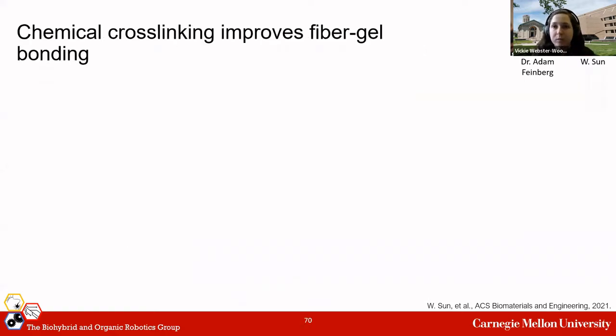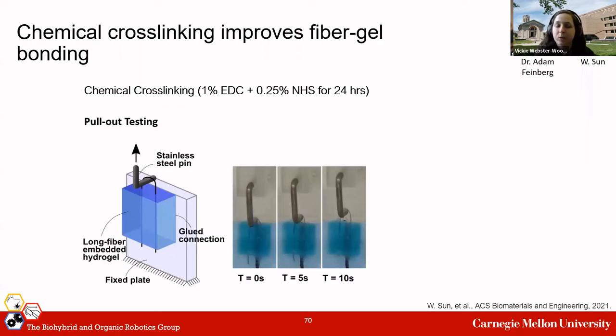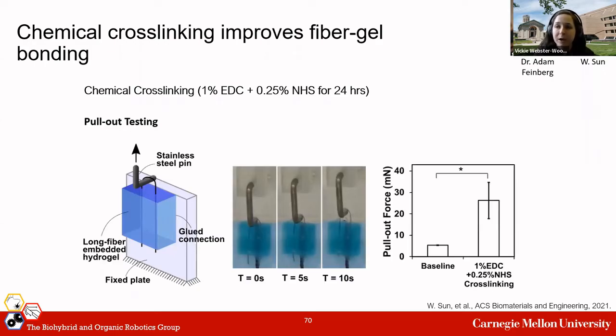For applications where robust thread gel adhesion is needed, we also tested for this interaction through a series of pull-out tests. We found that the initial pull-out force required was pretty low, but that we could increase adhesion strength through cross-linking.